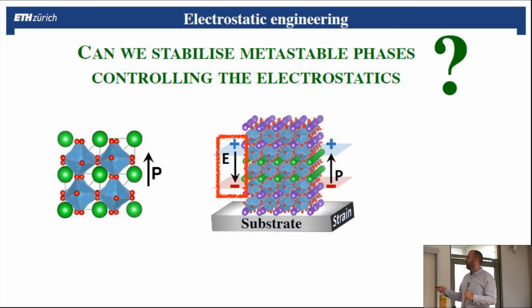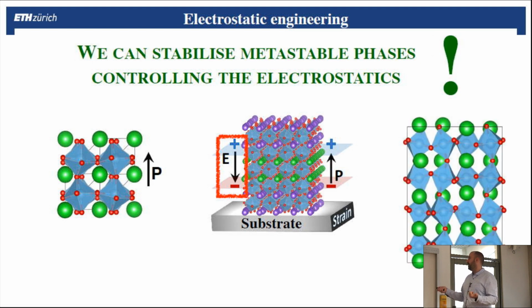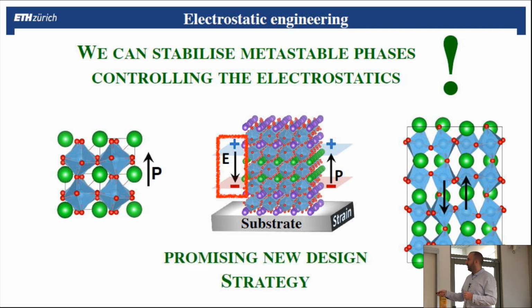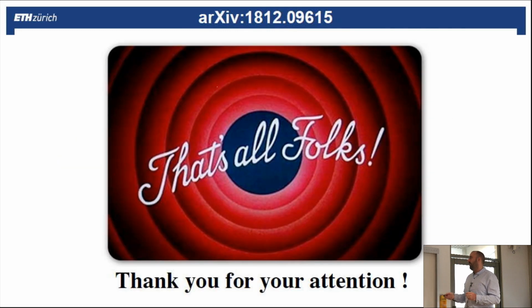So the question I asked initially was, can we stabilize metastable phases controlling the electrostatic? Meaning, can we go to a phase that is not the ground state by controlling what happens at the interface? The answer is yes, it was actually achieved, and we identified this non-polar phase that turns out to be actually also antiferroelectric, which is interesting for application. So that shows a promising new design strategy in order to build other antiferroelectric materials or find different properties by not only controlling strain, which is always done, but by also controlling the electrostatic at the interface.